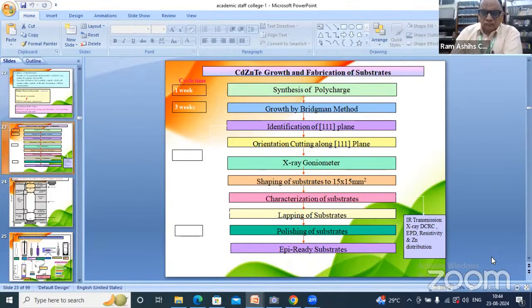For synthesis of the polycharge, we are using 7N pure cadmium, zinc and tellurium, and the selected method is the Bridgman method. After crystal growth, identification of the 111 plane and orientation cutting along the 111 plane. We are using an X-ray goniometer for plane identification. Then shaping of the substrate to the required size. Earlier we were using 15 by 15 and now 25 by 25 is required for device application. And substrate preparation by lapping, polishing, and making the substrate epi-ready for epitaxial growth.